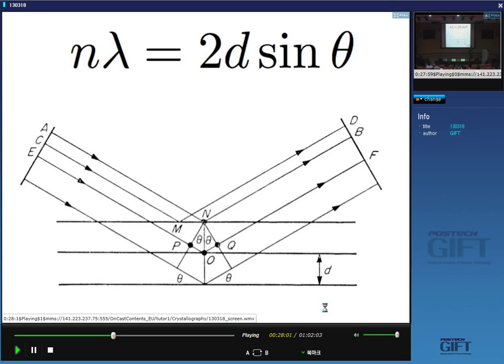Okay? So the Bragg law strictly applies for an infinitely thick crystal. When you look at very, very small crystals, your diffracted beam will have a certain width. Otherwise you should only get a single point at the angle theta where all the intensity is concentrated, right? So this is why when you're looking at small crystals, the diffracted intensity is spread out, not just at theta, but around theta as well. Same applies to X-ray diffraction, where when you're looking at very small crystals, you will get the beam being wider. Okay, so that's a crystal size effect.